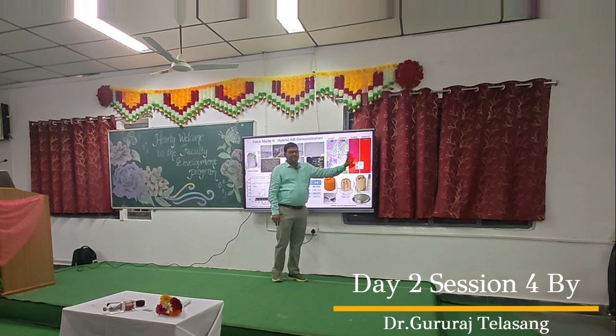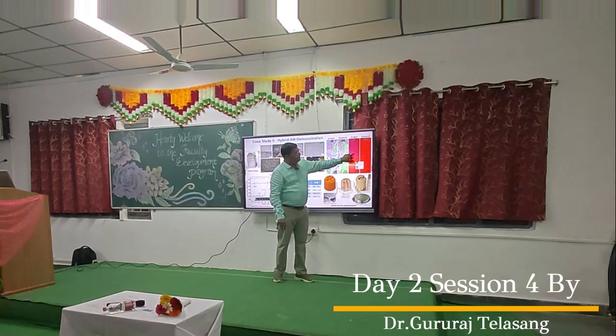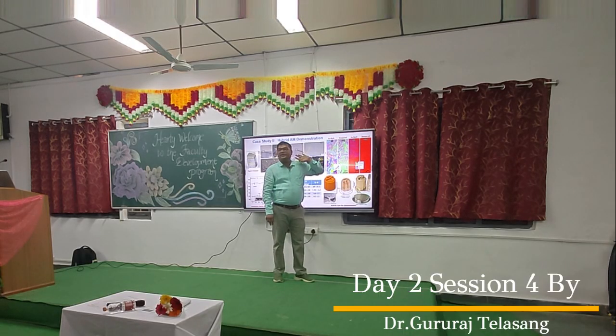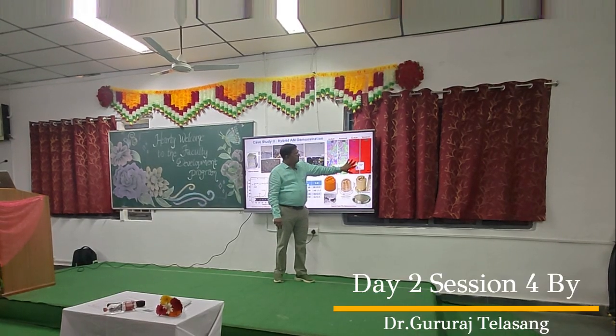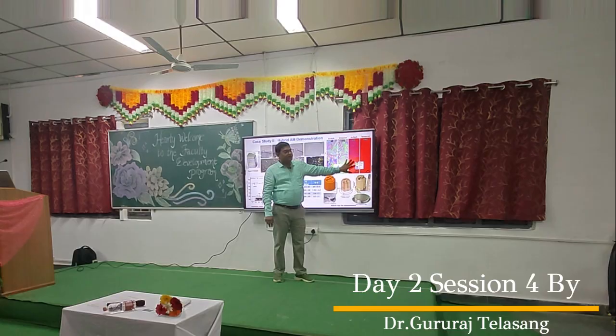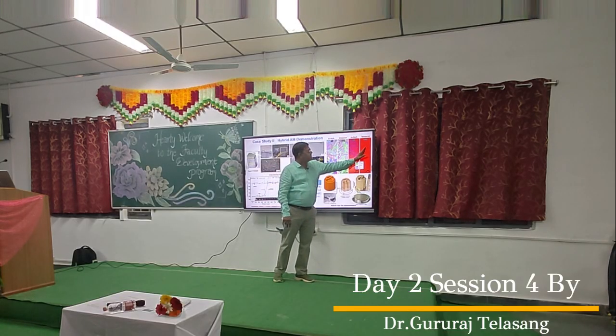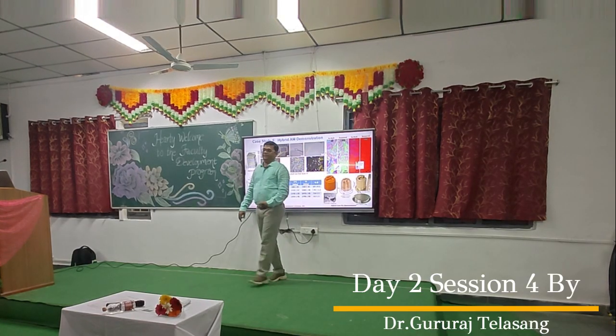So that's what you will see here. This is a phase diagram. This is a color orientation diagram. So here, blue things are retained austenite. Have you heard of austenite? Ferrite, martensite, austenite. Yeah. So this is retained austenite. This is a conventional soft anneal. There is only ferrite. When you do heat treatment, all these things have gone. That is another advantage of heat treatment. These dots are all carbides. And again here, no carbides. Here there are big carbides, few, but here you will get fine, many.